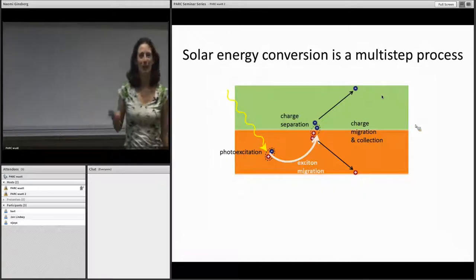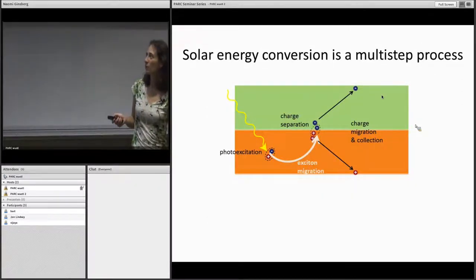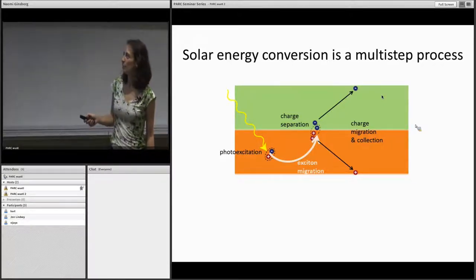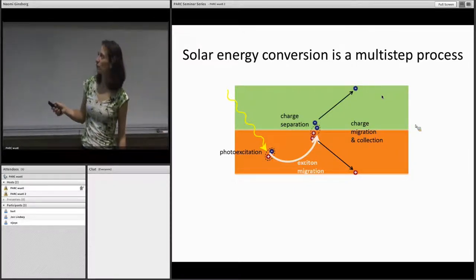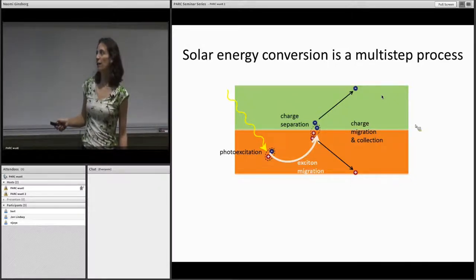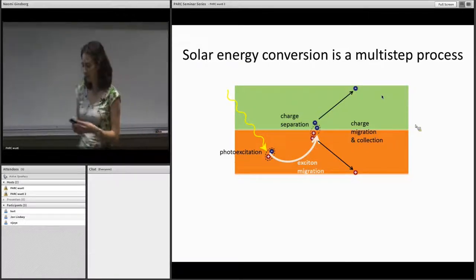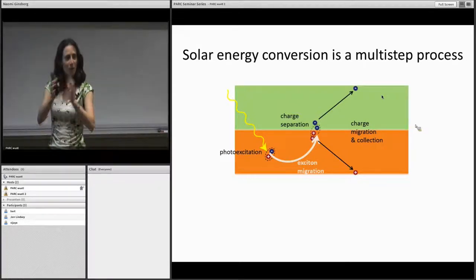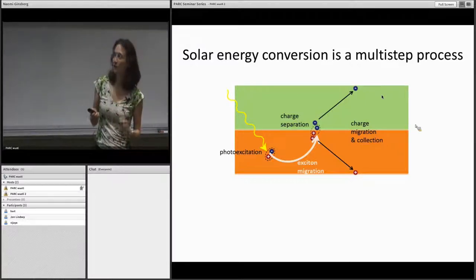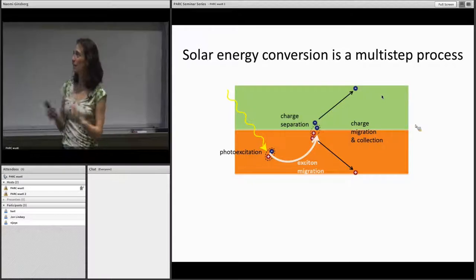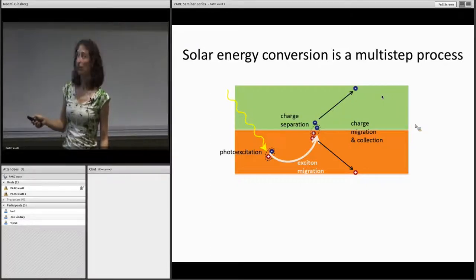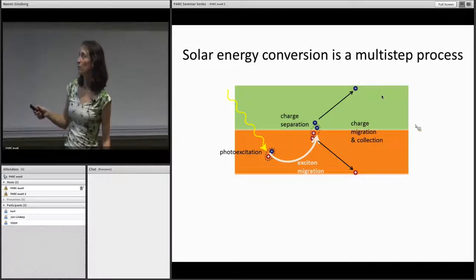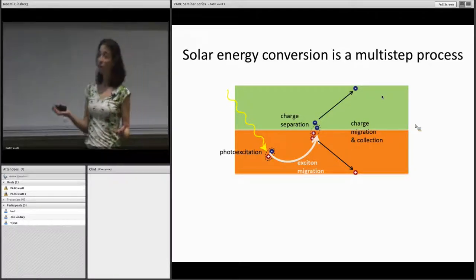You've probably heard people talk about the various stages important in converting solar energy into electricity, shown right here. If you imagine a junction between an electron accepting and an electron donating material, when you create an exciton using light absorption — especially in these organic materials — the molecular configurations are such that the excitons have very tight binding energies. This means they have to migrate rather far to get to an interface where charge separation occurs, and then you need to collect the electron and hole at opposite electrodes to get a photocurrent or photovoltage.